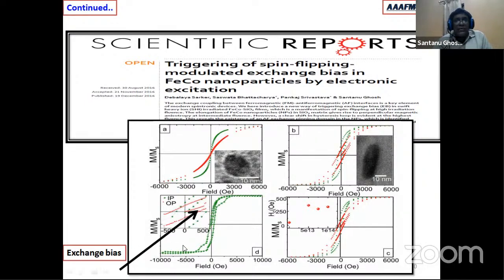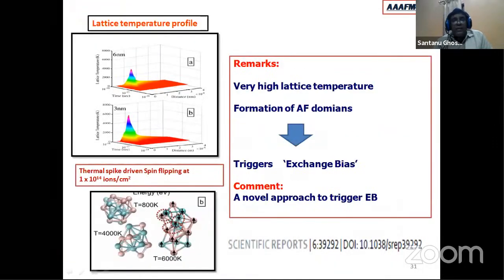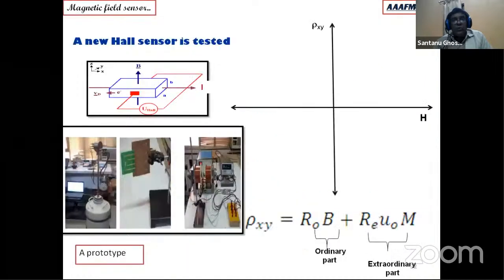What we have observed is the exchange bias effect. You can very clearly see that there is a shift in the loop, and this could not be simply explained, because there is no core shell or oxide on the ferromagnetic metal particle system. It is only after DFT calculation that we have seen that there is an intrinsic formation of antiferromagnetic domains because of that high temperature, and we have noticed that it's a novel approach to trigger exchange bias, which is extremely important for magnetic storage.